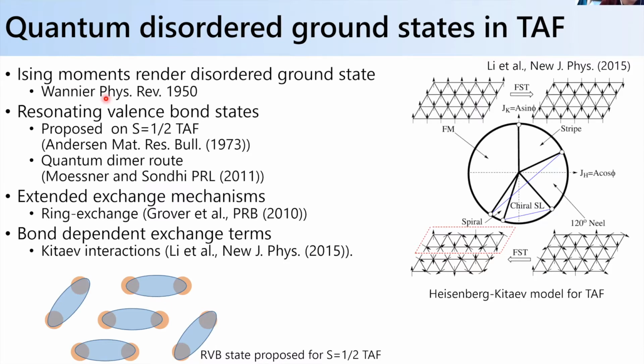And so, for instance, predictions have been put forward if you were to add strong anisotropies into the model, so moving away from the Heisenberg limit, looking at strong Ising moments. Resonating valence bond states have been proposed and different forms of dimerization. And you can realize some of these by adding anisotropic exchange interactions, such as Kitaev interactions, or ring exchange interactions, or other types of extended exchange, to create a more highly frustrated magnetic state, which never realizes a long range ordered magnetic ground state.